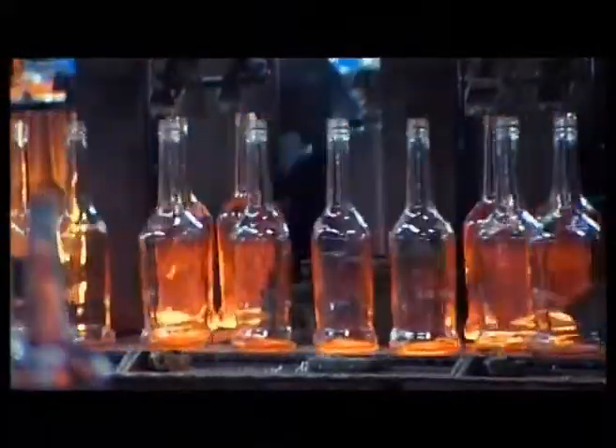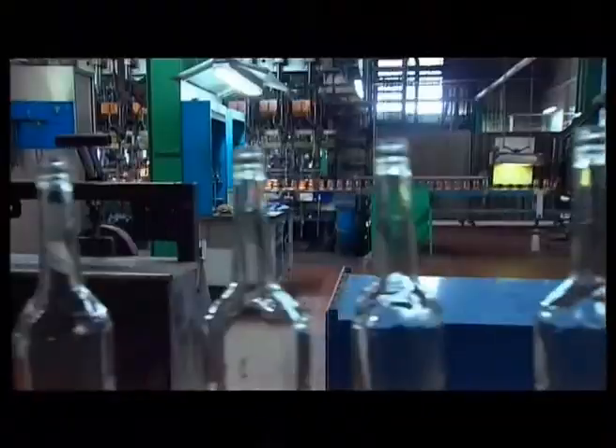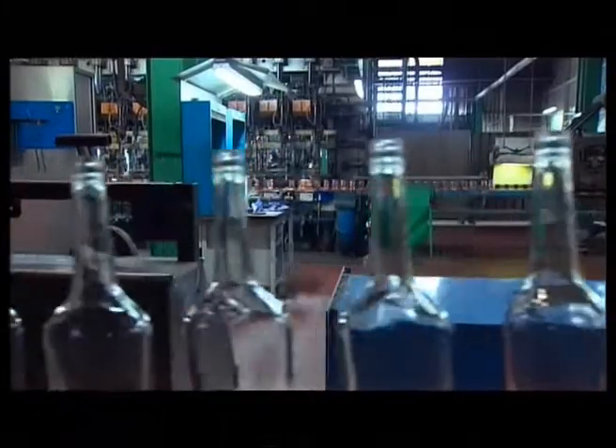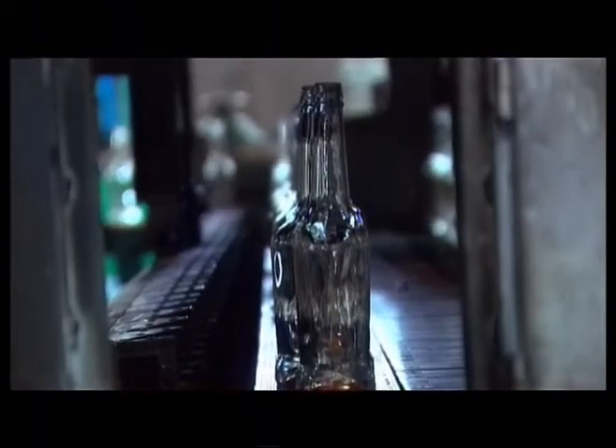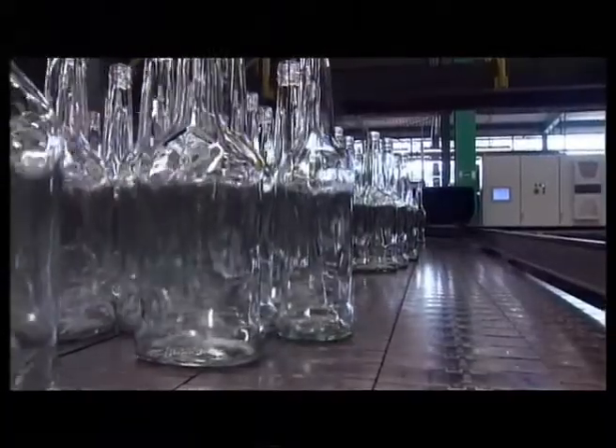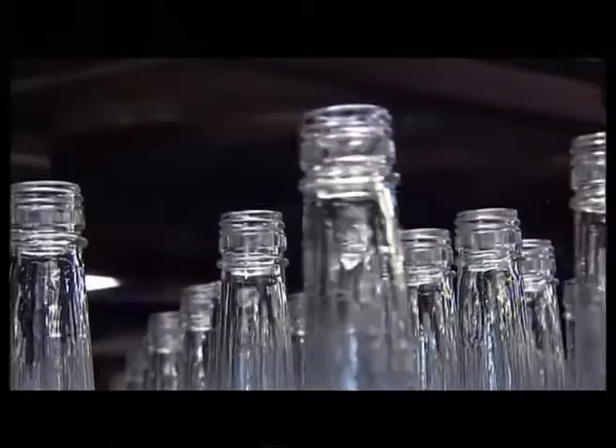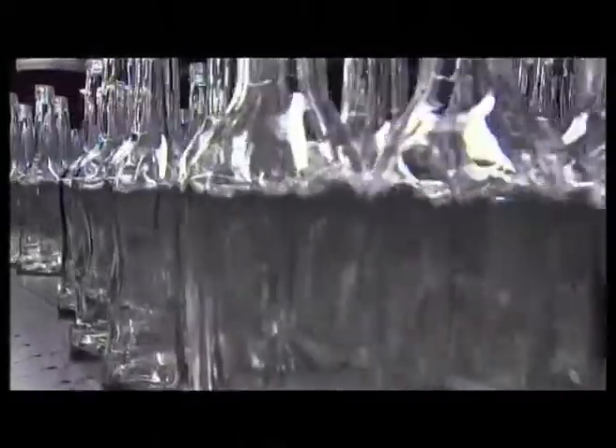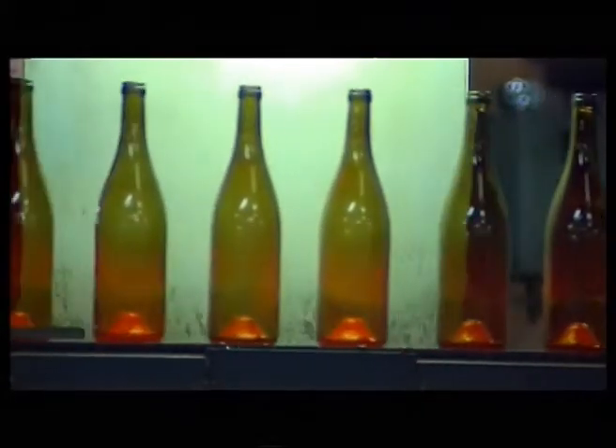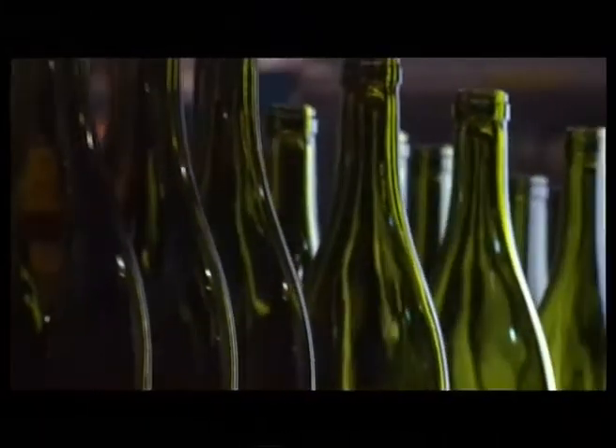At this stage, an annealing oven keeps each batch of bottles at a temperature of about 560 degrees before slowly cooling it. Cooling glass too quickly will cause it to become brittle and easily shatter. After the temperature falls below 100 degrees, the finished bottles can be taken out of the annealing oven. This glass factory will create everything from wine bottles, juice bottles, jam jars, pickle jars, fish pickling jars, beer bottles, mineral water bottles, to a new bottle of champagne.